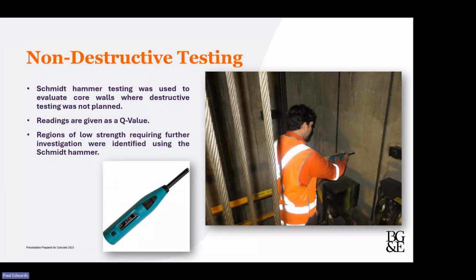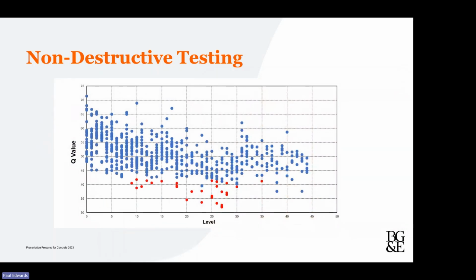And so a starting point for a lot of this was to do large amounts of non-destructive testing using Schmidt hammer. This enabled a relatively rapid understanding of the overall building's concrete existing condition, and then therefore enabled areas which were potentially below desired strength to be identified. So here there's a graph which shows Q value on the left, in effect a shorthand for the compressive strength of the concrete at the various floor levels along the bottom axis. You can see that there's a zone indicated by the Schmidt hammer testing around the mid height of the building, which potentially isn't quite at the desired concrete strength that the design would require.